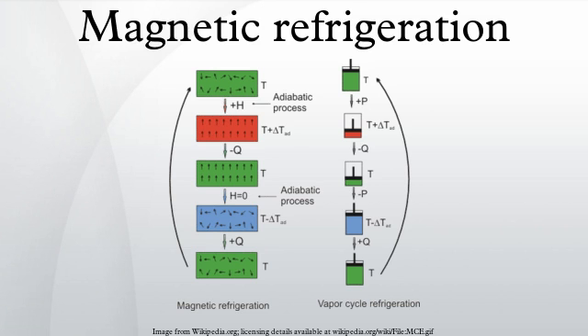The magnitudes of the magnetic entropy and the adiabatic temperature changes are strongly dependent upon the magnetic order process. The magnitude is generally small in antiferromagnets, ferrimagnets, and spin glass systems. It can be substantial for normal ferromagnets that undergo a second order magnetic transition, and it is generally the largest for ferromagnets that undergo a first order magnetic transition.